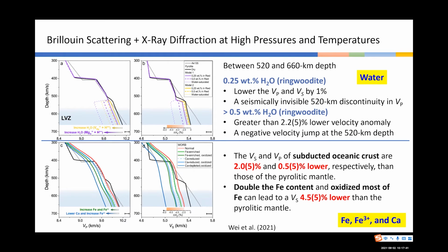So how about if water is present in both octahedral and tetrahedral sites of ringwoodite? In this case, let's look at the purple line here. The solid purple line means less water content, and the dashed purple line means water saturated condition. If ringwoodite contains more than 0.5 weight% of water, you can see that yes, it can cause more than 2.2% reduction in the shear wave.